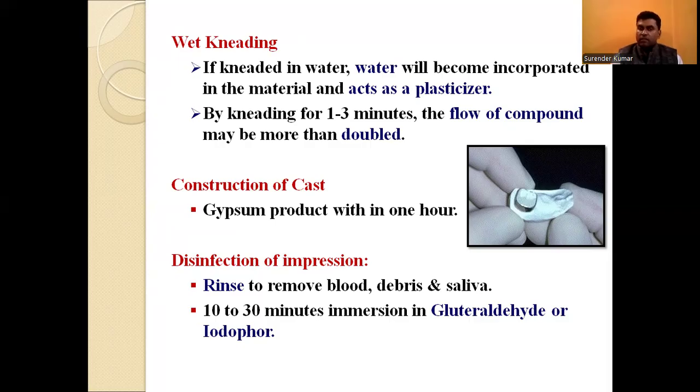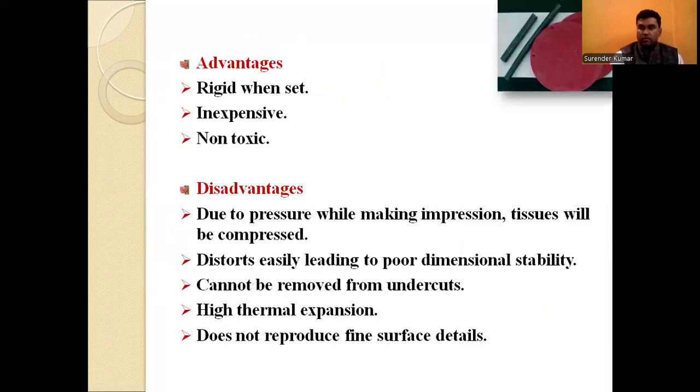Construction of the cast: after that, a gypsum product is used to pour the impression, within 1 hour. Disinfection: remove the debris and saliva, rinse it first, then you can place it in glutaraldehyde or iodophore for 10 to 30 minutes.